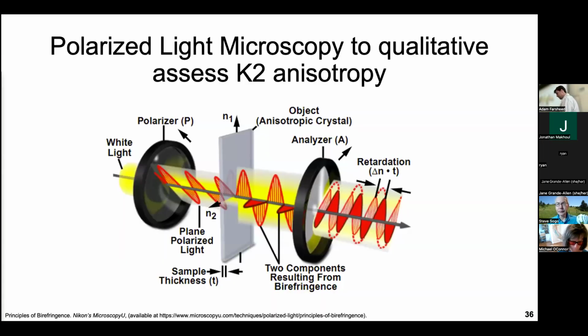So I went ahead and did a series of screening studies using a technique called polarized light microscopy that I want to just quickly give an explanation of what we're looking at. When you take white light and you place it through a polarizer, similar to polarized sunglasses, that light is going to be polarized into one plane. And if you have a cross polarizer in front of that, that's basically polarized orthogonally, you're going to cancel out all of that light.